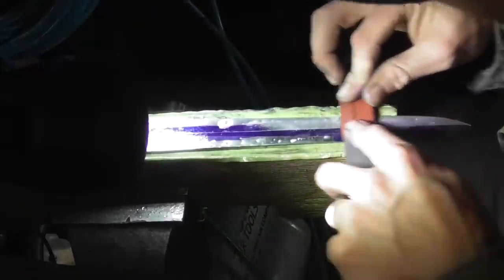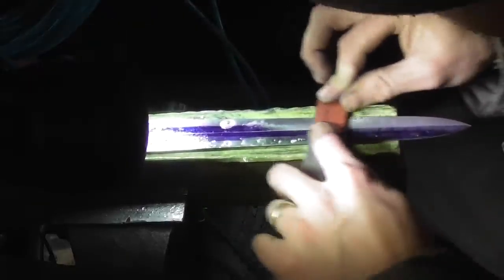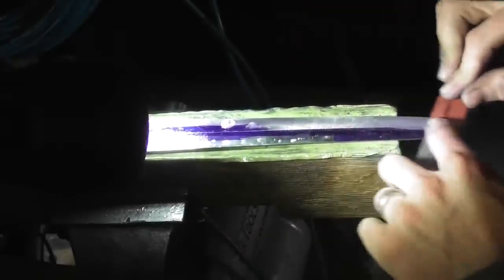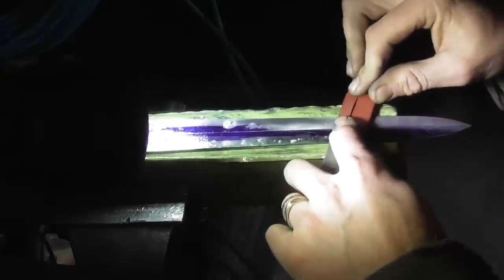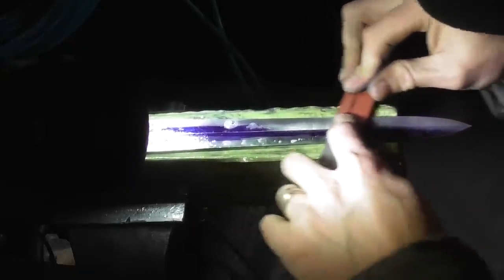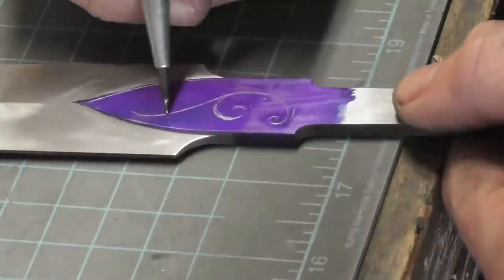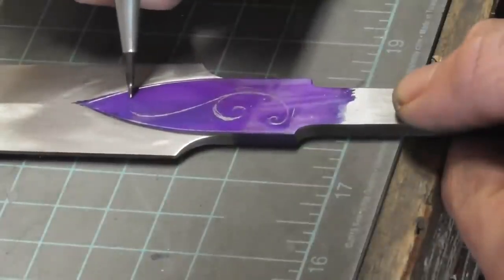Time for hand sanding on the entire blade. Start with a 320 grit and then go up to 600 and then 1,000. And I want to go in alternating directions each grit to make sure that I get out all of the scratches from the grit before. I'm also using a pretty thin and firm backer to make sure that it's as flat as possible.